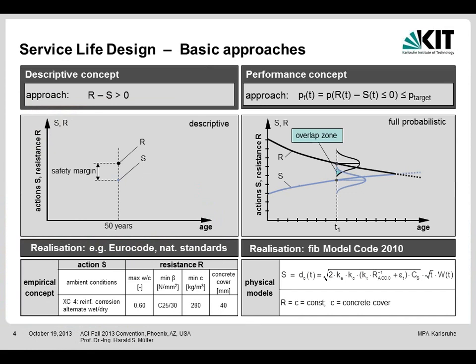Much better is a performance concept. You have the same formula here, but now you have the probability of failure, and you calculate with time. And you have an additional parameter, which is the target. This means it is a limit state. You define a limit state. And now you can have functions of the resistance and the actions, and you see here I can scale the axis. Here nothing is scaled, and now I can do an exact calculation of resistance and the actions, and then I can calculate how much cover I need and so on for all the parameters. This is realized in the fib Model Code 2010.